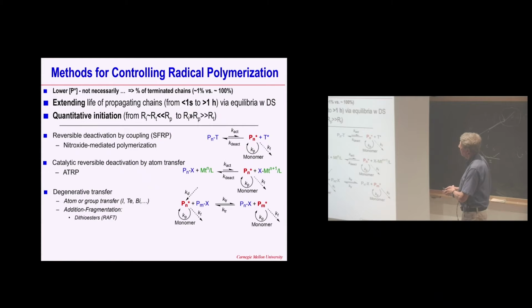So if you have below 1%, I think you should be happy, 99% preservation of the chain ends, 99% block copolymerization yield. And another very important issue is that you would like to extend the life of propagating chains from seconds to hours, just to make these synthetic manipulations much easier. So conventional radical process is slowly initiated, and after 1 second, all chains are terminated, essentially. And here we would like to extend it to maybe hours or maybe even days.